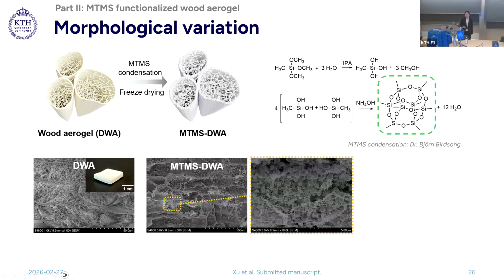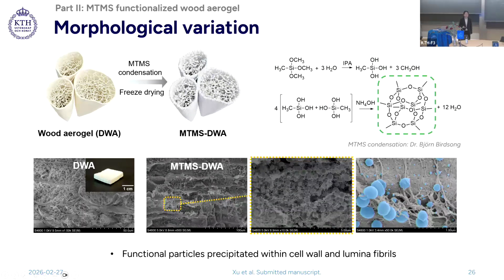Microscope images show that the MTMS condensation largely preserves the lumina fibrils. The newly formed spherical particles are either trapped within the porous cell wall or intertwined with lumina networks. In other words, here, in addition to the cell wall, the lumina fibril networks also provide nucleation sites for particle deposition.